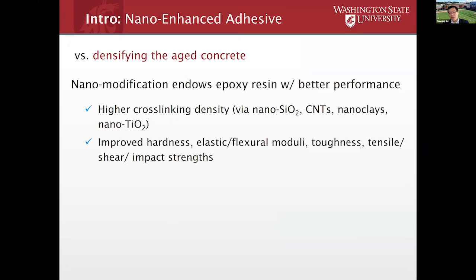So our thought process was, okay, instead of trying to densify the aged concrete, we might be better off relying on the FRP and enhancing one of the weakest links in the FRP, which is the adhesive. I think Alex earlier implied there may be some challenge with the UV aging unless you put a top coat on top of the FRP, but arguably the adhesives are usually epoxy resins. They are not only vulnerable to UV aging, but also to water. When exposed to wet-dry cycling, the epoxy can get more and more brittle and eventually crack.